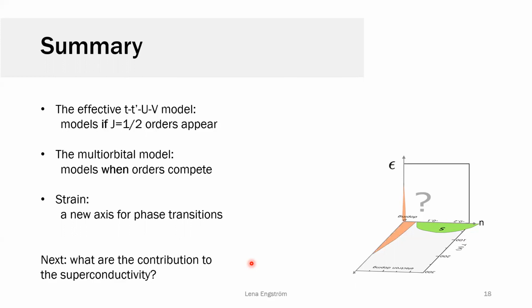The way we can use this is that we can start looking for whether we could possibly have superconductivity when increasing the strain. Because we know from the general predictions for this type of superconductivity that it does appear once you have a smaller antiferromagnetic order. So since we can manipulate the order and the different components, it's possible that we could see superconductivity in this regime, but it's also possible that we could change which orbitals contribute to the superconductivity. So you might not just see the standard cuprate superconductivity, but it is possible in this model to see some more exotic superconductivity. Yeah, and that's pretty much what I'm working on.